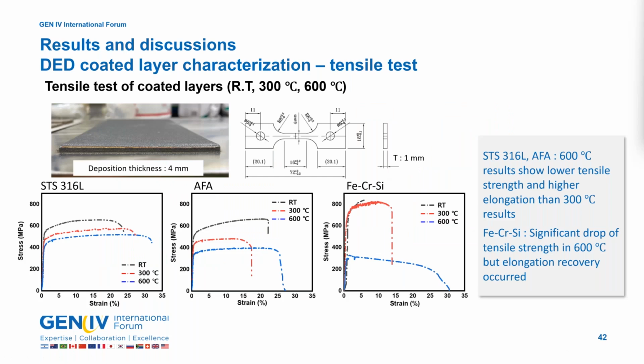Since the developed materials may be exposed to high temperature environments, tensile tests were conducted at room temperature, 300 degrees C, and 600 degrees C to determine their strength. To prepare the high temperature tensile test specimens from the deposited parts, samples with a thickness of more than 4 mm were fabricated, and test specimens were extracted from the deposited sections.